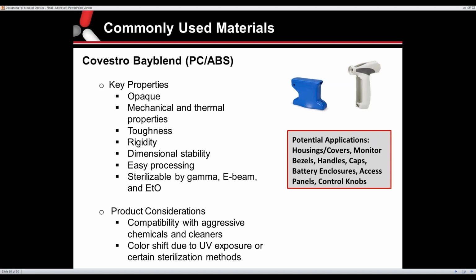You get great dimensional stability. The processing temperatures are lower, so this product is actually a little bit easier to process. You usually get real good surface finish, and it can be sterilized multiple different methods, including gamma, E-beam, and ETO. So because of the nature of the good balance of properties with a PCABS, it's a real nice material for housings.